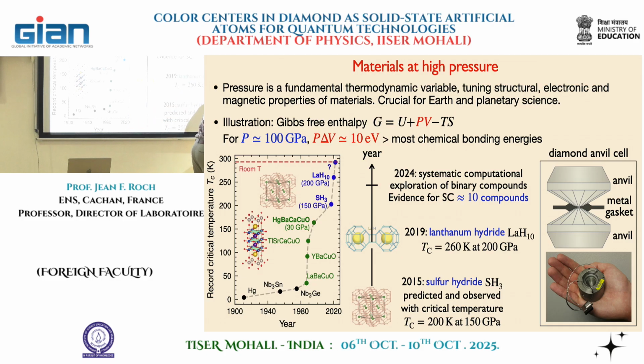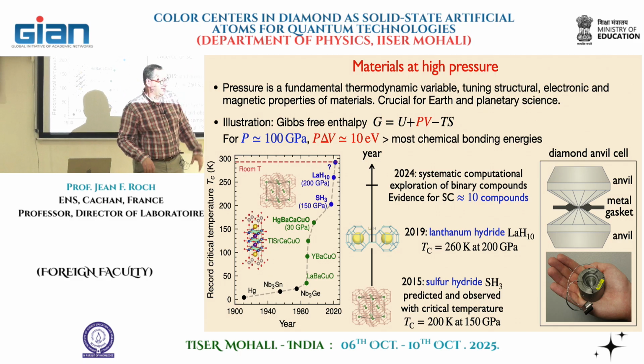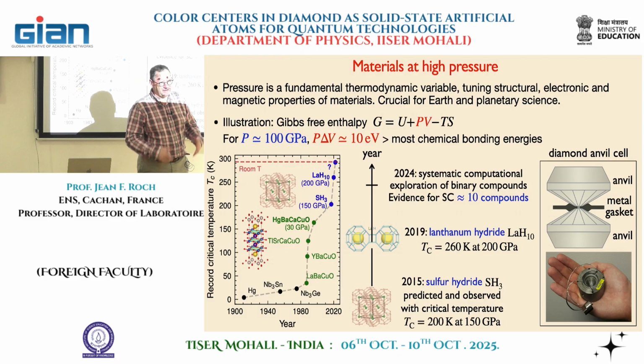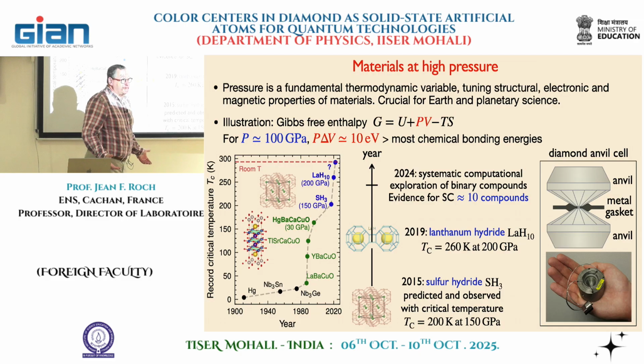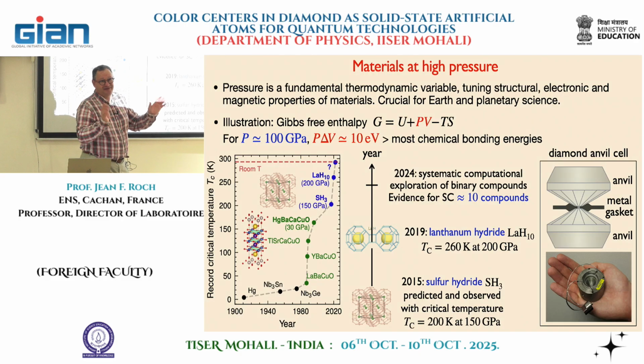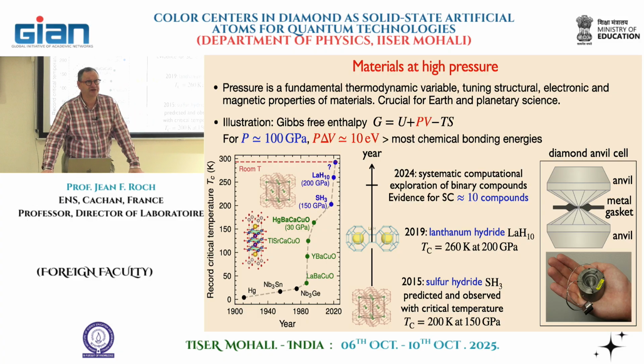And the pressure is controlled here with this tiny capillary tube that you see here. And there's a tap here. You close the tap, and then you can have your sample at 100 gigapascal and keep it forever if you want. And there's almost no leak, of course, because if there is any leak, then everything will be removed. So this is very nice, and this has been found in the 50s, and there has been a lot of technical development on how to use the anvil. There have been remarkable discoveries found using this tool.